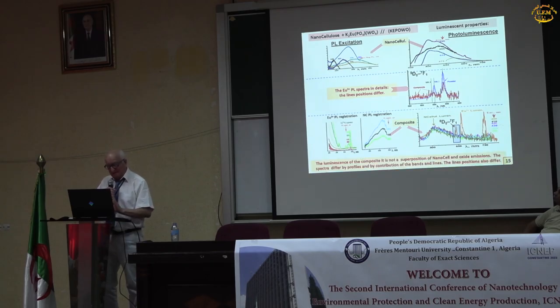So we can conclude that the luminescence of the composite is not a superposition of nanocellulose emission and oxide particle emission. The spectra differ by profiles and by the contribution of the bands and lines. The line positions also differ. You see that in the middle of this slide.